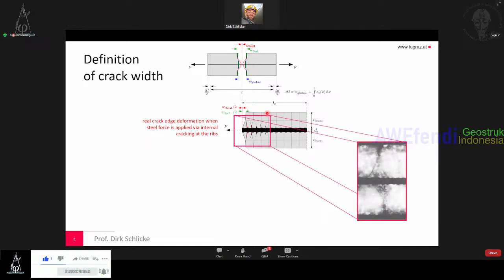This was also measured here with some X-ray. This is from a German PhD, where you see this crack root. There's the primary crack. Of course, it's somewhat smeared because it's X-ray through the entire bar, and there's some shading in this. Anyway, what you can see is that these internal cracks are very pronounced near the primary crack, and the more you get away from the primary crack, the more the internal cracks also diminish.